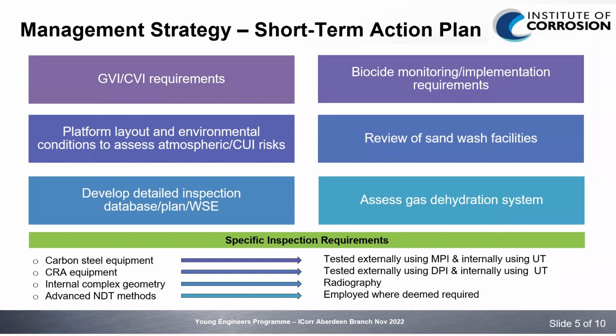As I said earlier, the sandwash facilities, none of the information we've received actually indicates that there's any online sand washing going on. It just indicates that there's the bulk removal of sand at shutdown. So we'd potentially like to review that so that we can avoid further problems such as the possible MIC that we've seen in the first stage separator. We'd also like to look through the gas dehydration system, because it's been noted that downstream of the contactor, there's actually potential upsets in the drying process, which obviously there shouldn't be. We've got carbon steel after then, and that's at high risk if the gas isn't dry.